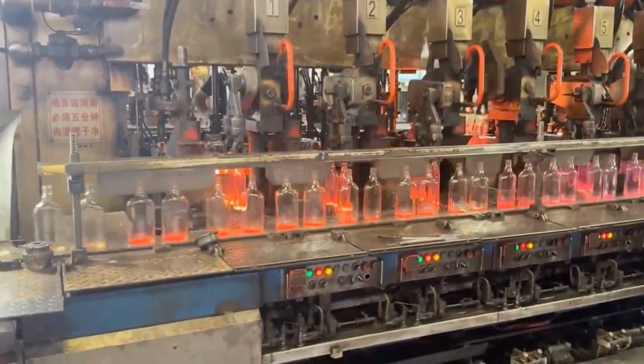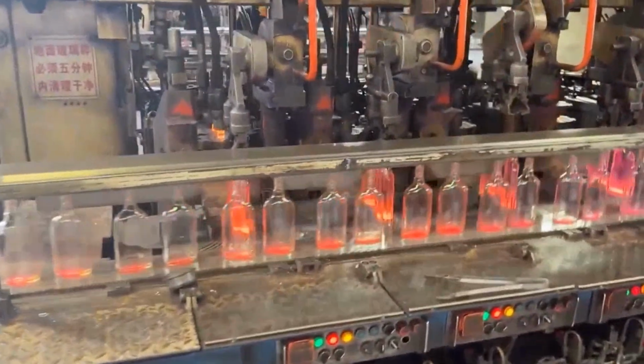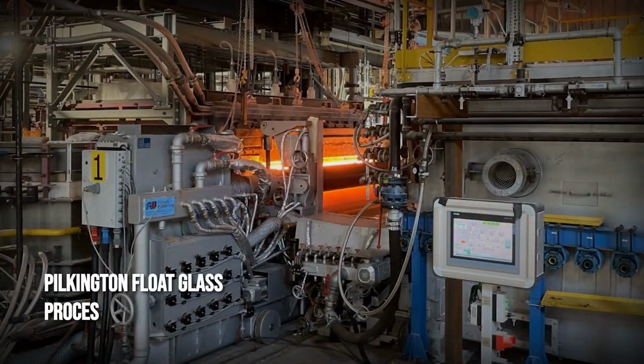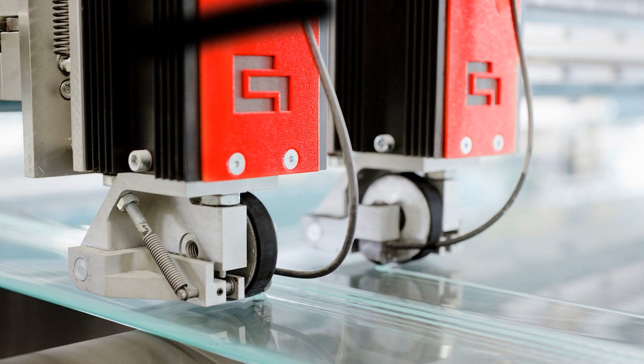With the molten glass primed at just the right viscosity, the next act unfolds on the forming lines, where a single river of glass splits into 3 distinct destinies. For float glass, the Pilkington process takes center stage. Here, a glowing ribbon pours onto a bath of molten tin, kept under a protective atmosphere of nitrogen and hydrogen. The glass floats effortlessly, spreading out into a perfectly flat sheet, its underside untouched by air or roller.